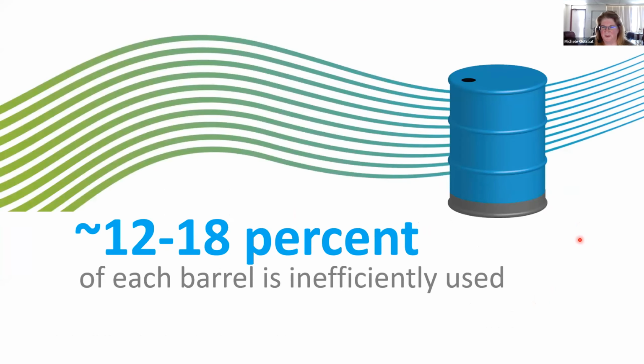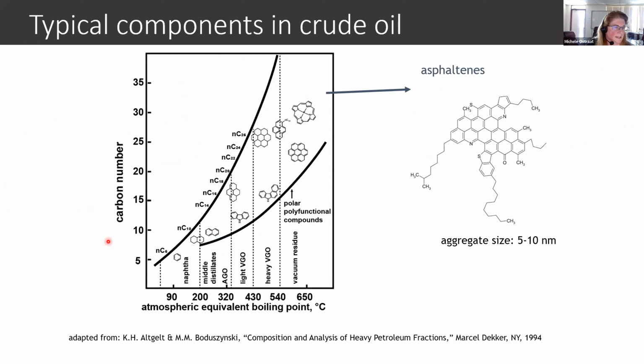But now this is where the sustainability point comes in. Not sure how many people in the audience know this, but from each barrel of oil, unfortunately, 12 to 18% of each barrel of oil is inefficiently used. This is material that is a very, very high boiling point. It's very, very viscous, very difficult to work with. It's called vacuum residue. And it's basically materials that can have upwards of 20, 30, 35 carbons per individual molecule. And it's very, very difficult to process these materials.